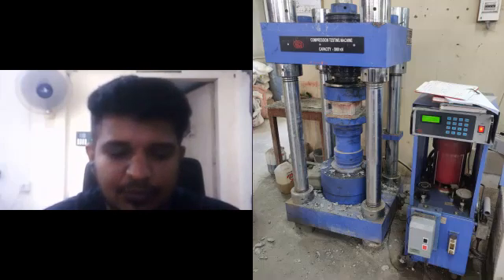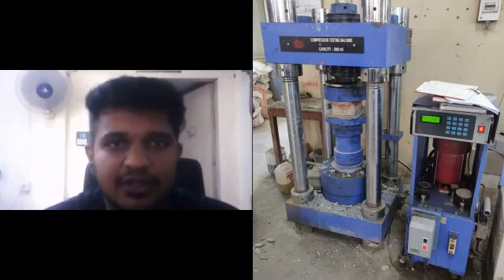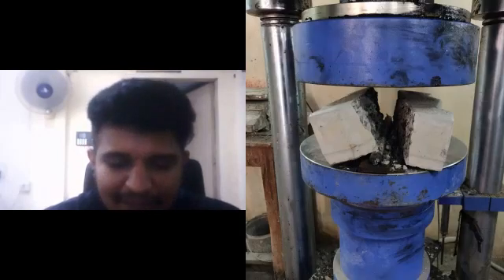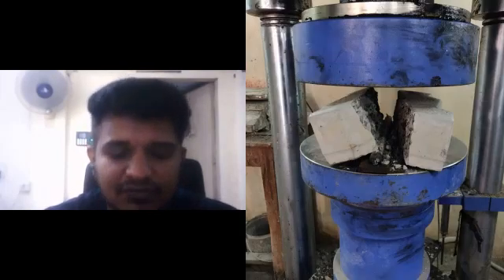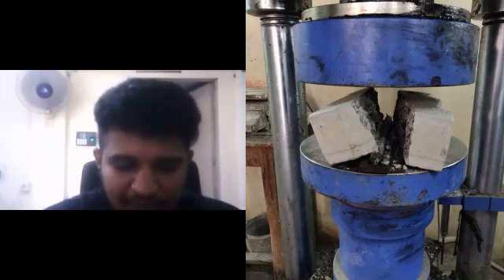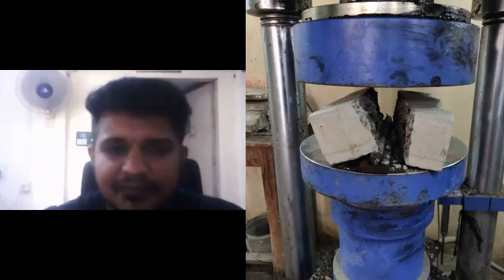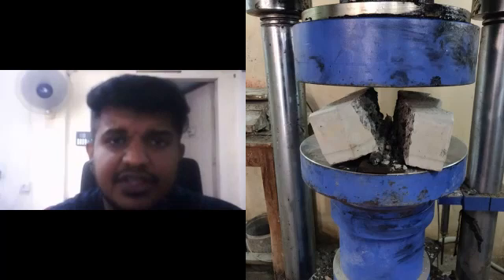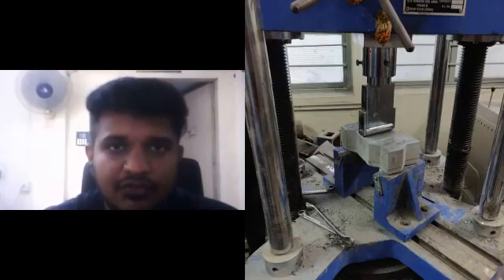I developed a new superplasticizer with a very high solid content that is not available commercially in the market. And this admixture was then added to a concrete mix that contained very high amounts of ash. See, in my mix design, I incorporated around 500 to 600 kgs of ash per cubic meter of concrete, which has not been achieved in the past in a commercially feasible manner. Geopolymers have done this, but they were costly.